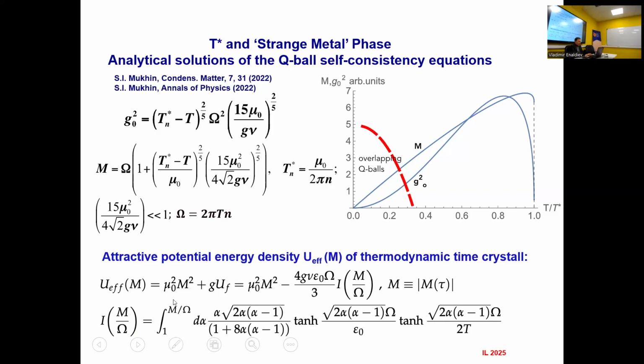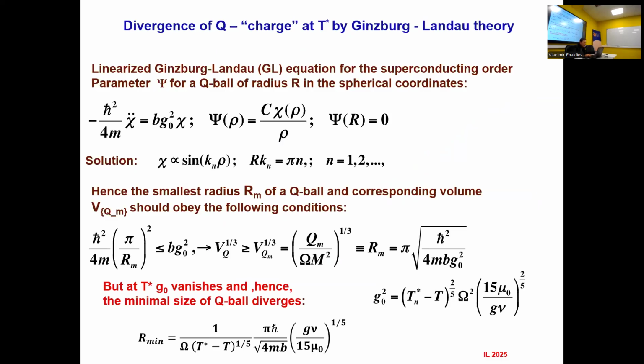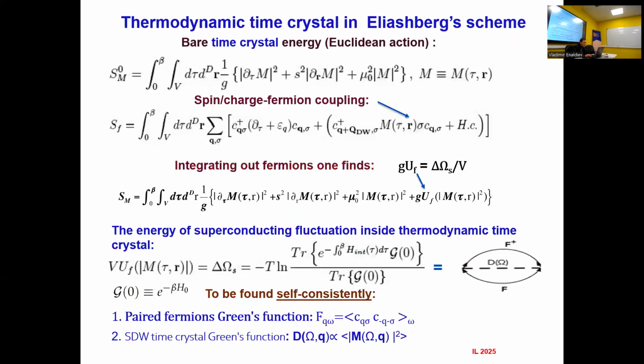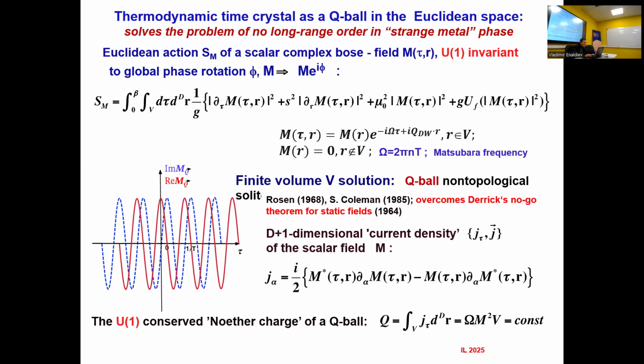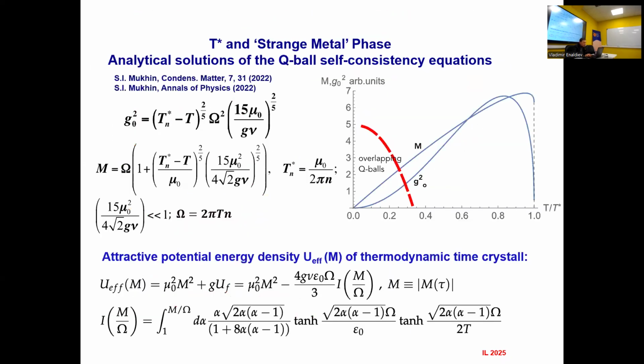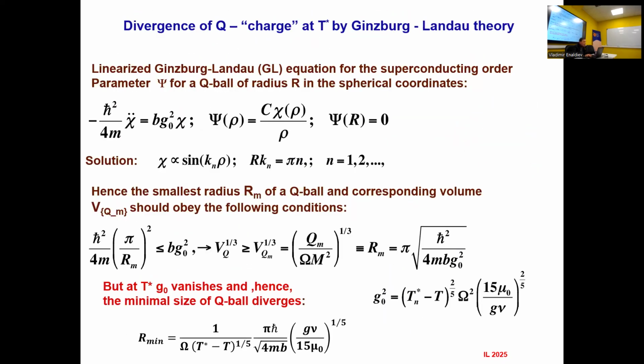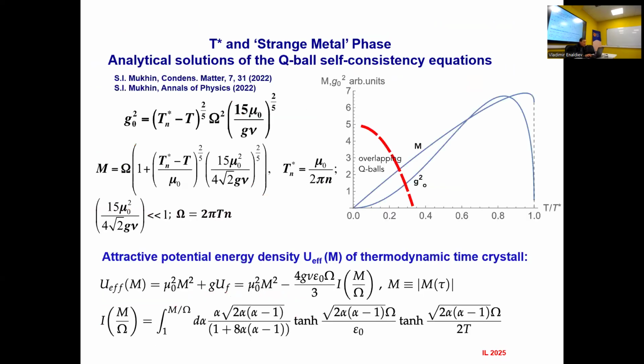Okay, so this is UF, and what you can do, you can now substitute this expression back into our self-consistency equation from which I started, and solve it for this M. So this was your question, what is M, how it depends on parameters, and that's very interesting what happens then. Yes, and if we do this, now one more important story. What happens when we are close to the T star temperature? When we are away, M is proportional to omega, but when we are close to T star temperature,